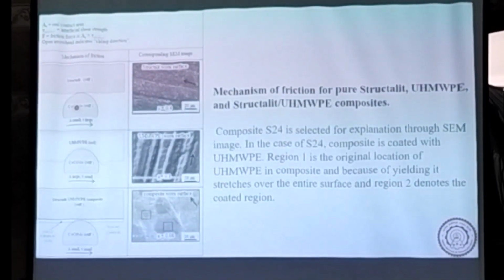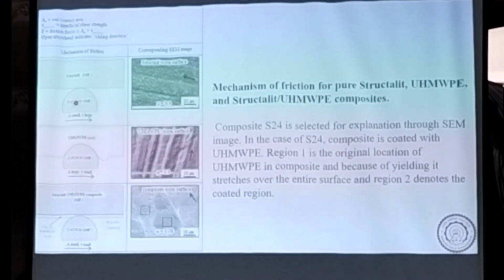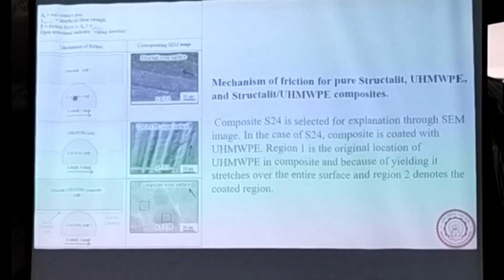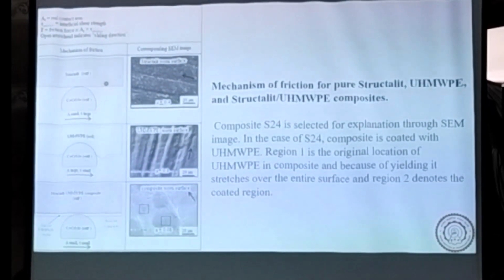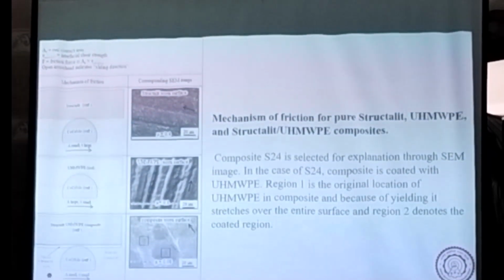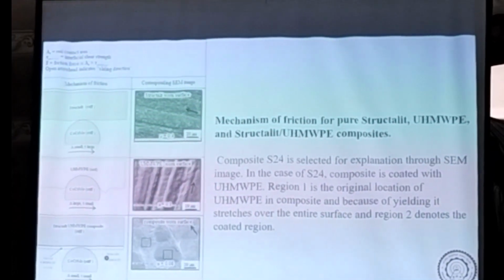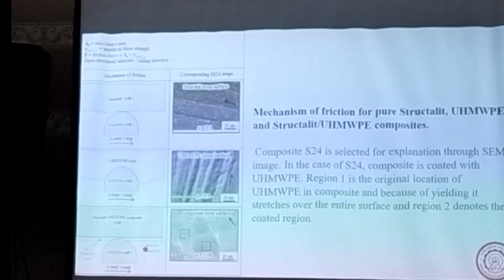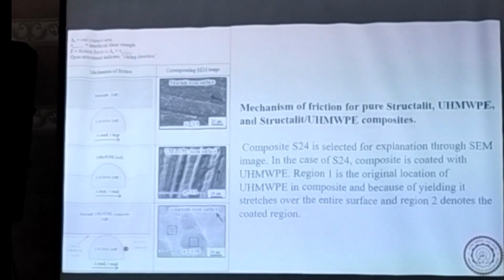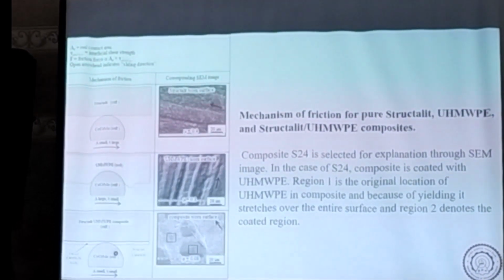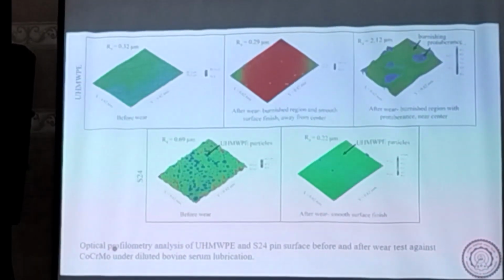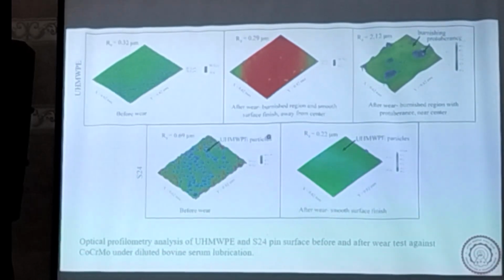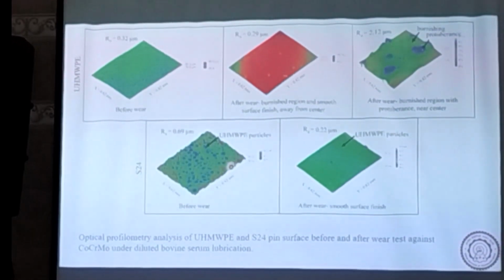And when you have two stiff materials together, in that case you have a lot of brittle fracture happening at the interface, and again friction is high. So we are in this situation where friction is low because of two hard materials with a soft interface at this point. The 3D profile of these two surfaces again tells us similar things to what the SEM picture has given.